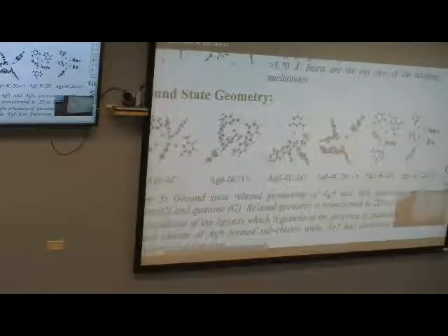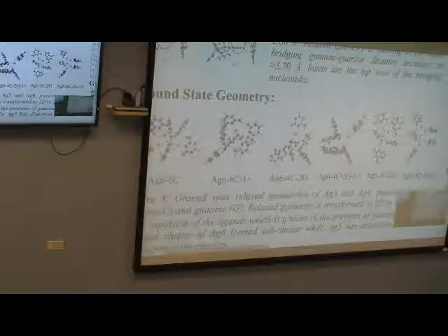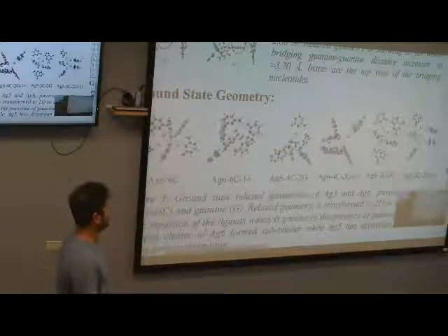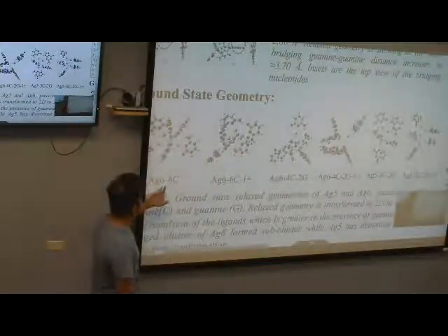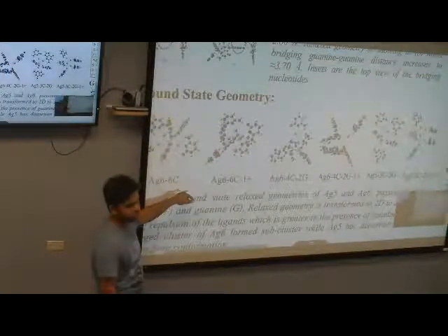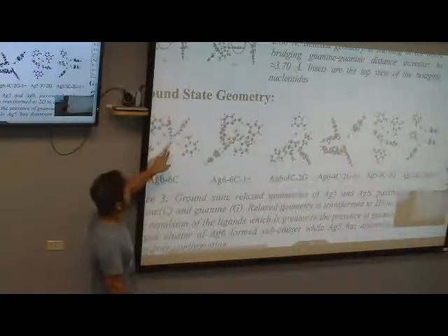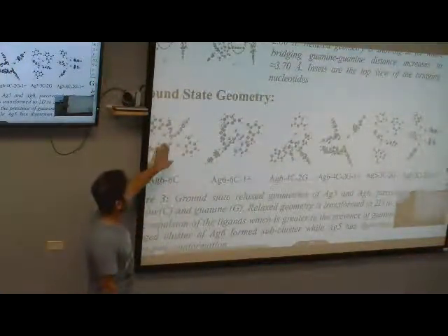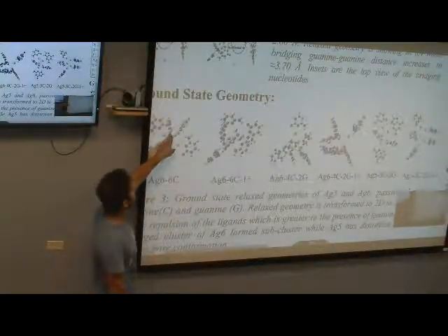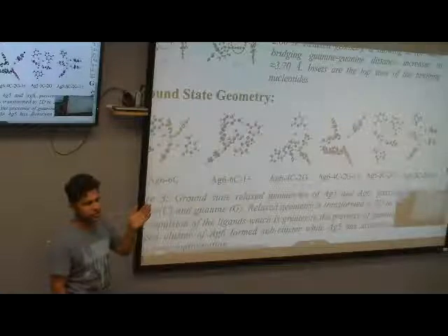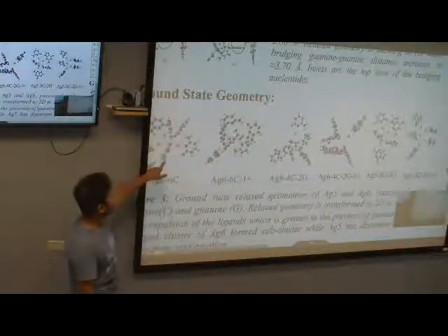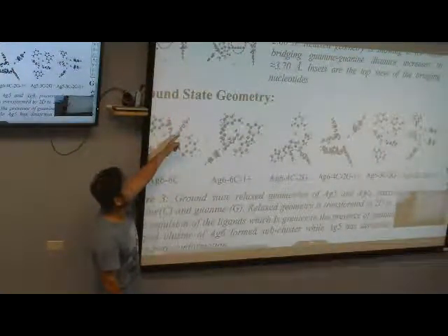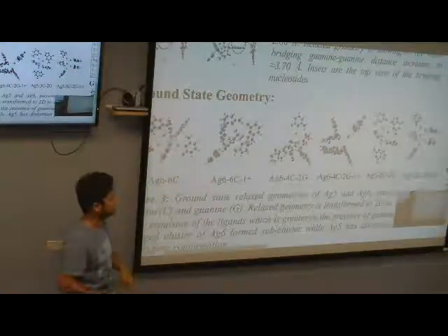So this one is an example of the optimized silver 6 cluster. If you look in here, this conformation is very important in this case. That's why I'm showing the conformation toward the final conformation of the cluster. This one is optimized with all cytosine, only cytosine. We started with the planar geometry, and after the optimization in the solvent medium, it keeps an almost planar geometry. This one is a little bit tilted, but it keeps a more symmetric structure. And this one is a little bit distorted from the planar because of repulsion between the cytosines.